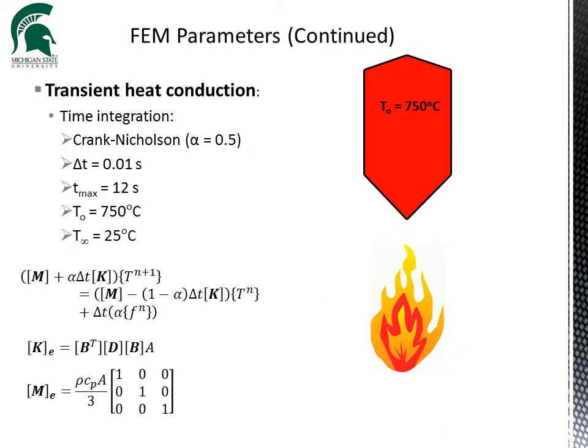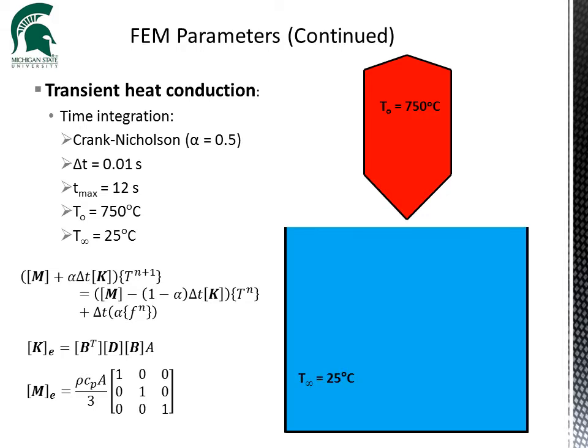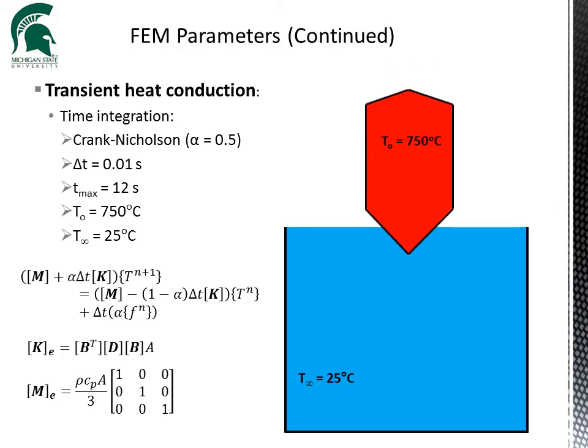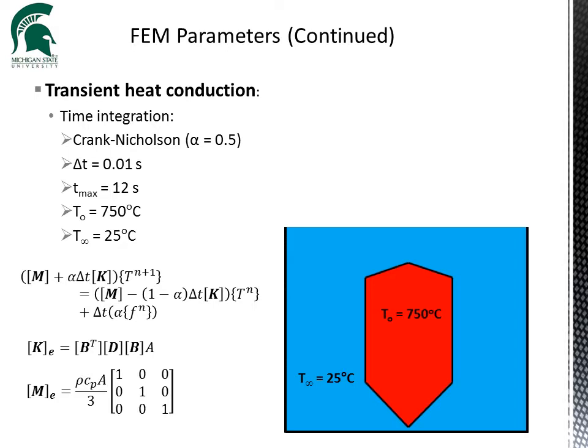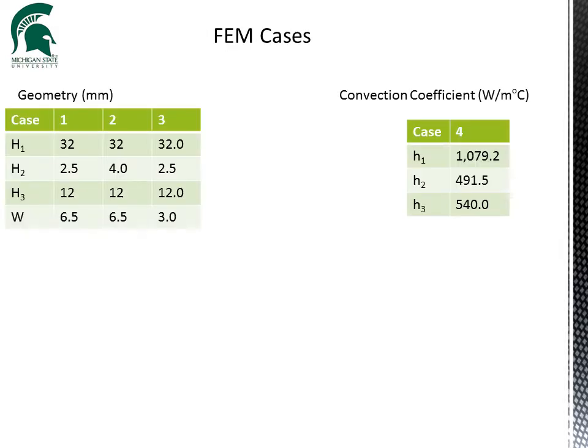Time integration is done by using Crank-Nicolson, by heating the sword to 750 degrees Celsius, plunging it in a bath of 25 degrees Celsius water, letting it cool, and arriving at its final solution. Now, 3 cases were looked at, varying the height dimensions and the width, as well as the convection coefficient.